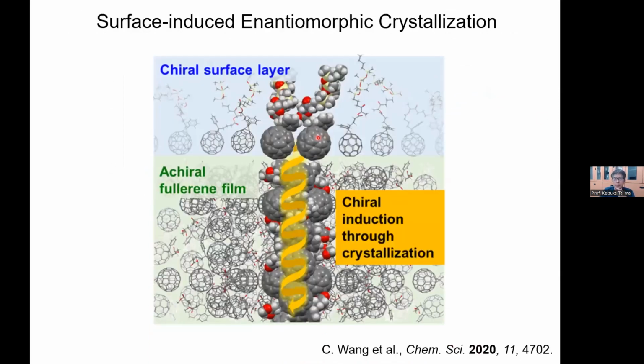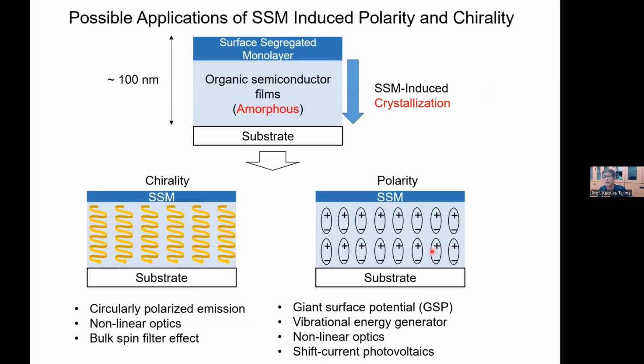So here's the summary. Chiral induction through crystallization can be induced from the surface. We don't have an application for this phenomenon for now, but I think this really opens up a very interesting possibility to control the crystal structure in the film. Generally, the surface monolayer can induce chirality or maybe polarity. We are still working on this possibility inside the film.